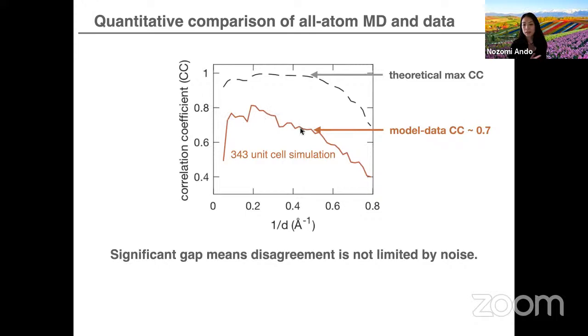And this was already a huge improvement relative to what had been seen in the field. But it was telling us that even with state-of-the-art MD, we couldn't really get the agreement that we needed in order to be confident about the interpretation of the trajectories that we would get from MD.